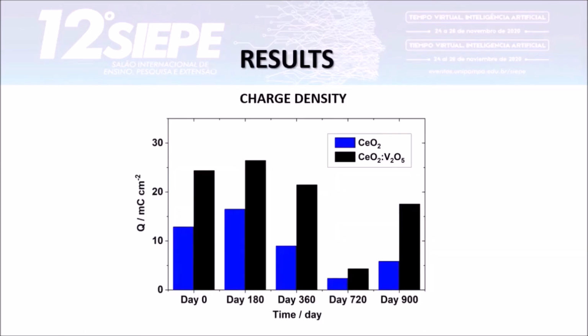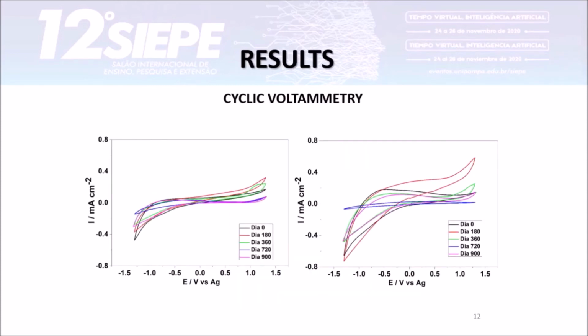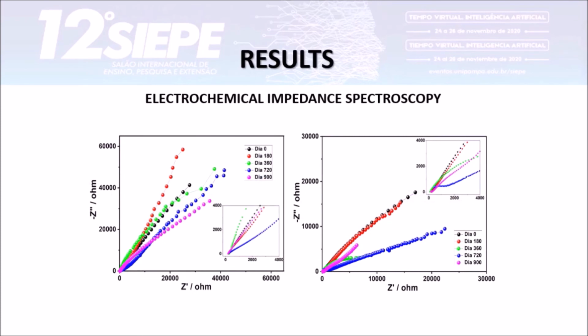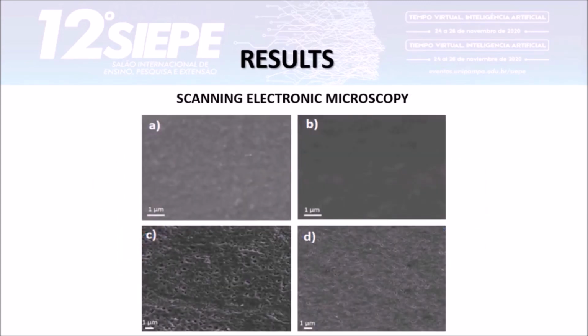By chronocoulometry, it was possible to study the charge density. The films presented some variations during the process, but the doped film presented better results in all analyses. The cyclic voltammetry presents a higher area for the doped film, which is the one on the right. That means that there are more paths for the ion movements. By the impedance analysis, the Nyquist plot presented a 45 degrees angulation, which means that the charge transport occurs through diffusion. Through SEM, it was possible to observe that for all films, pre- and post-weathering, there are some cracks and irregularities on their surface.